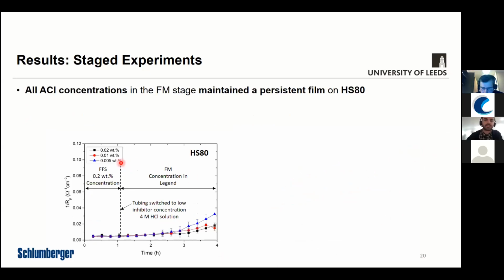So we moved on to the staged experiment. Like I said, we would have the film forming stage for 1 hour, switch the tube into the low concentration, and then we'd continue the film maintenance stage for the different, much lower inhibitor concentrations than during the first stage. So obviously we've got 3 different lines on this graph, but during the first hour, all the inhibitor concentrations are exactly the same. But beyond that period, we have the different concentrations which are listed here.